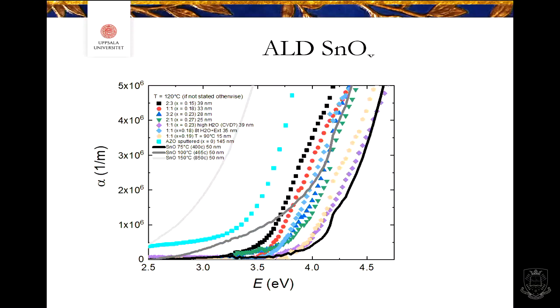As you can see, even though the thickness is the same, we have a very different band gap. I have maybe not talked about the band gap so much, but you see the alpha here is the absorption coefficient. Here we have low absorption, and then when the absorption goes up, that means there is the band gap. So this is a wide band gap electron conductor, with a big variation in band gap just because of how you deposit the layers. And of course we want the band gaps to fit our material, so there is easy electron transfer. The current goes easily from the perovskite layer to the electron conductor layer, just as well as we want the holes to be easily transported in the material. So not too big gaps, because if it is that, then we have recombination in the solar cell instead.